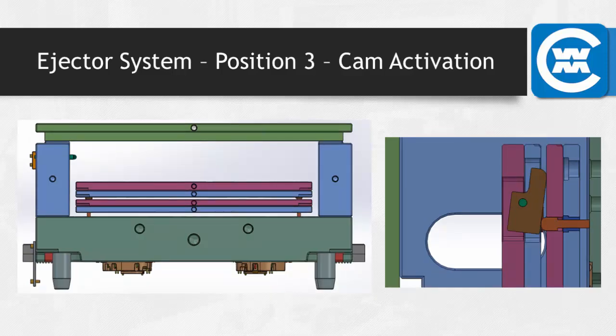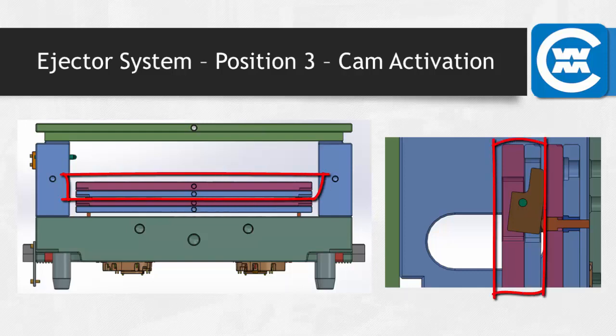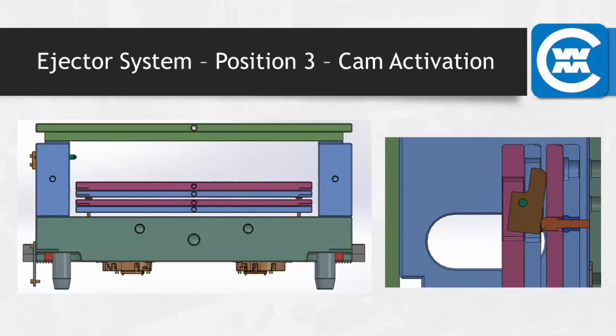So this next position is what we call the cam activation. The ejection system moves just a bit further forward from position 2. So plates 3 and 4, these back two here and these two right here, move that same small amount forward, but due to the cam rocking forward and pushing plates 1 and 2 even further forward, the kicker pins activate and the casting falls off the rest of the pins. So the casting is now in the quench pit and we're ready to return the ejection system to position 1.